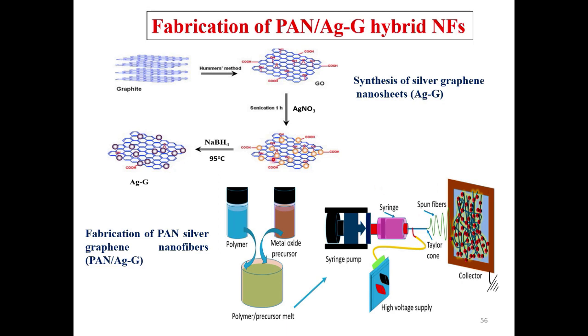Then fabrication of PAN-AgG hybrid nanofiber. Initially we synthesize graphene oxide from graphite using Hummers' method. That graphene oxide is formed, and meanwhile we synthesize silver nanoparticles with the help of silver nitrate. Both solutions we combine with sodium borohydride as a reducing agent. There is a formation of silver graphene nanosheet. This sheet is called AgG, meaning silver graphene nanosheet.